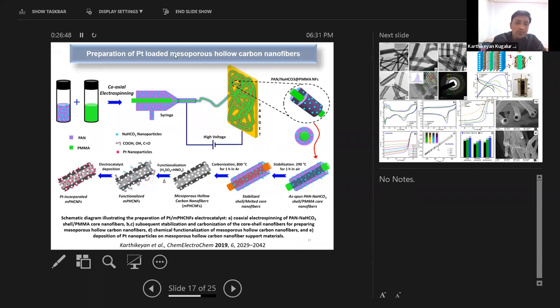Similarly, we have also fabricated the mesoporous hollow carbon nanofiber using a coaxial electrospinning setup, as I explained earlier. So there will be two parts, the outer part and the inner part. The inner part will be supplied with polymethyl methacrylate solution, which will be removed finally. And the outer part will be filled with polyacrylonitrile solution, which is mixed with sodium bicarbonate nanoparticles. When you are using the electrospinning technique for producing nanofibers, we supply a high potential difference. During that time, the polymer solution will be deposited as nanofibers. These nanofibers will be treated with a thermal annealing process. So finally, you will get the porous carbon nanofiber.